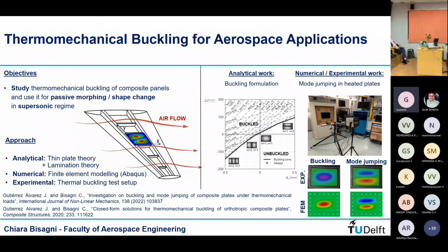Another work for a PhD that just graduated a couple of months ago was about thermomechanical buckling of aerospace structures. So buckling not only driven by mechanical load like compression or shear, but also driven by thermal loading. So the idea is as for a supersonic aircraft, because you have already the thermal loading there. But we investigate both analytically, numerically, and experimentally.